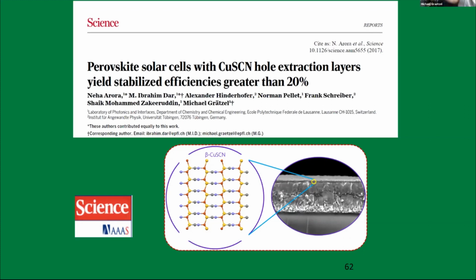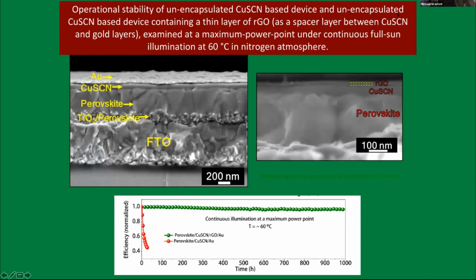But we did go back because we discovered something new. We discovered that it sufficed to put some reduced graphene oxide film between the copper thiocyanate and the gold back contact to stabilize the performance. And you can see that here now we got really over 1,000 hours at 60 degrees maximum power point tracking. No change. If we don't have the graphene oxide, this thing declines very quickly. And this also shows you that these cells are, compared to silicon, very thin. They use very little material, and I dare say maybe several hundred times less material than silicon. So the cost of these materials is very, very low. And given the fact that they can be applied from solution, they are a tough competition for silicon photovoltaics.